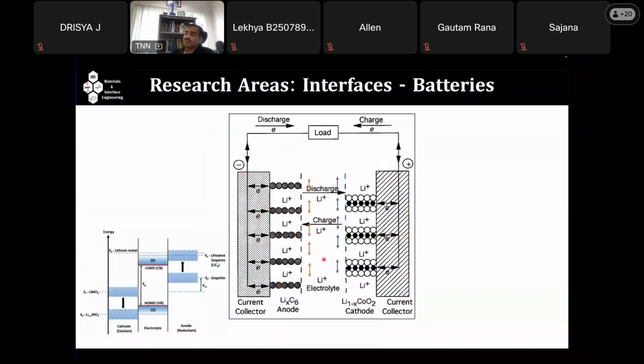What will happen during this initial charging and discharging process, the electron and lithium ion shuttling, is that some of the electrolyte gets interacted with the electrode, and then there will be a solid electrolyte interface formation. This solid electrolyte interface will have different composites, different organic and inorganic materials, and this optimized organic-inorganic mixture interface will stabilize the anode and cathode for the electron transfer process, or make the electrolyte stable. What I mean by that is that if you don't have such a stable solid electrolyte interface, then the electrode can interact with the electrolyte continuously.